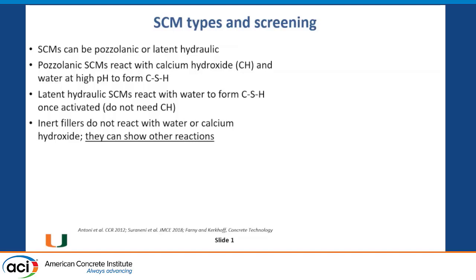Pozzolanic means that these materials react with calcium hydroxide and water. This reaction really happens to a significant extent at high pH, and the product that's formed is C-S-H. On the other hand, latent hydraulic SCMs do not need calcium hydroxide — they can react with calcium hydroxide, but they don't need it. They react with water once activated to form C-S-H.